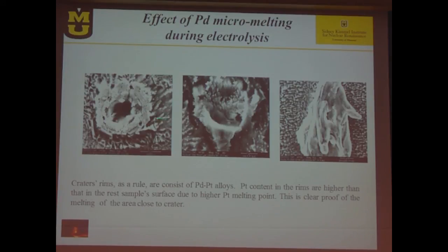But around the rims, we found 15% of platinum, which means, according to the phase diagram of palladium platinum, that melting took place. Now, melting is about 1500 degrees centigrade, and this is immersed in a solution. So you can imagine what was the temperature in these craters. So we thought that this is the source of heat. So in order to find some correlation, you need to scan the whole surface step by step and to find some figures of merit. The problem is that it's a very costly process to scan a few centimeters long cathode. It will take 28 hours, and it's not cheap, and it's almost impossible.